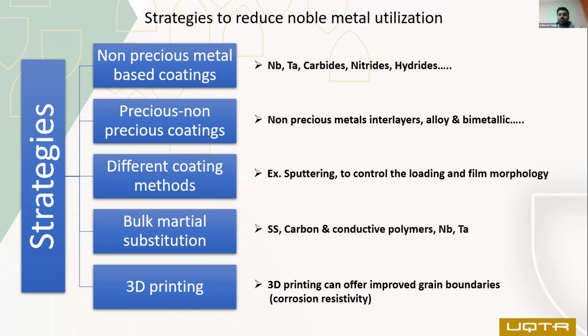Different coating methods also can help to reach the target. Like the sputtering method can precisely control the loading and desired morphology. That will also help to reduce the precious metal utilization, because the electroplating method, which is worldwide used and accepted by the industry for the coating of bipolar plates and the porous transport layers, PTLs, is very notorious